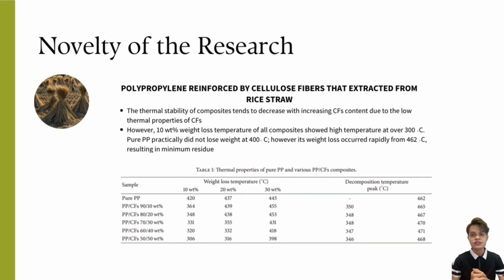The next part is novelty of the research. What is the difference of polypropylene reinforced by cellulose fiber based on different plants? Actually, there are many differences, but now I will highlight the weaknesses from the aspect of different plants. First, I will highlight the weakness of polypropylene reinforced by cellulose fiber extracted from straw. The thermal stability of the composite tends to decrease with increasing CF content due to the low thermal property of the CF.